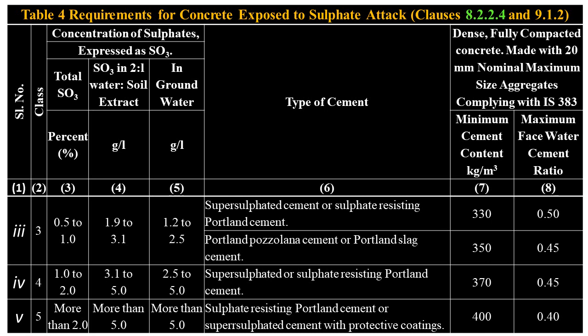Type of cements: supersulfated or sulfate-resisting Portland cement. Minimum cement content, 370 kilograms per cubic meter. Maximum free water cement ratio, 0.45.